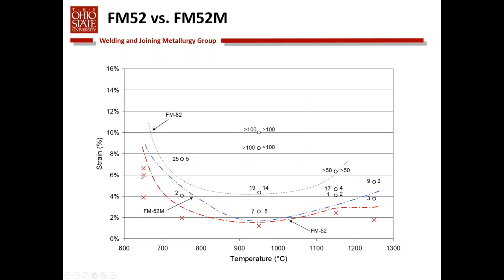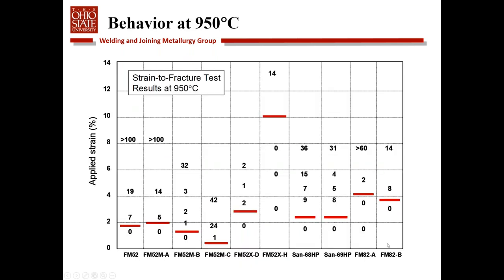So you can test over a range of strains and over a range of temperatures, with strains ranging from about 2% up to 10%. Again, we do not pull the sample to failure. We simply strain it, and then we go in and we count or measure the number of cracks that are present on the surface. And so we can develop these curves, which indicate the ductility curve for the material. Below the curve no cracking occurs, above the curve cracking occurs. And so this represents a ductility curve for the particular material.